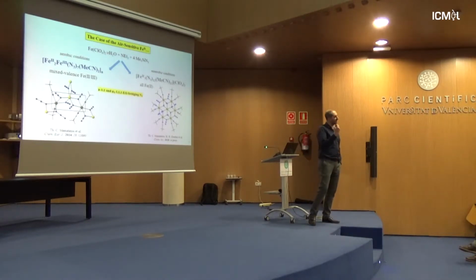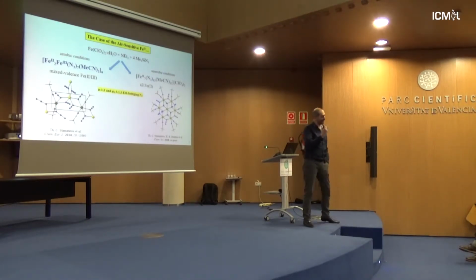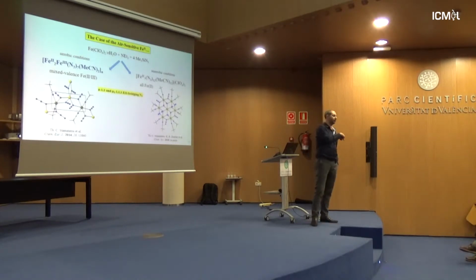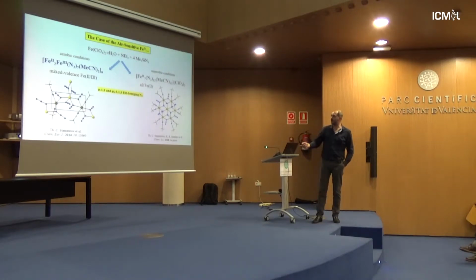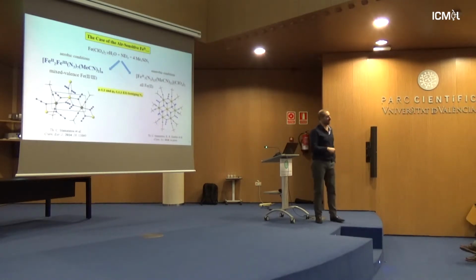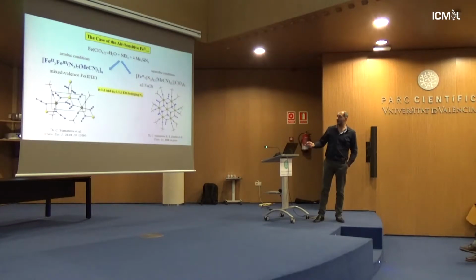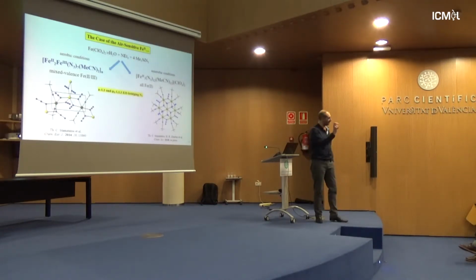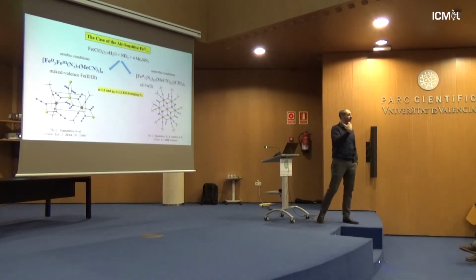Iron is very special, because the chemistry can be different when you work with iron 2+ or with iron 3+, or when you do the reactions under inert atmosphere or at room temperature. And this is where we got two different families of compounds. When we used aerobic conditions, starting from iron 2+, we were able to get a mixed valent iron 2+, 3+ compound, which is not actually a molecule, but a two-dimensional coordination polymer. We're going to see the structure in a while.